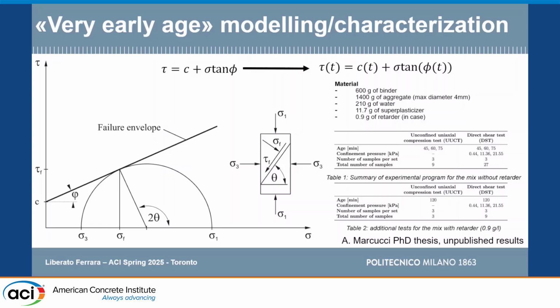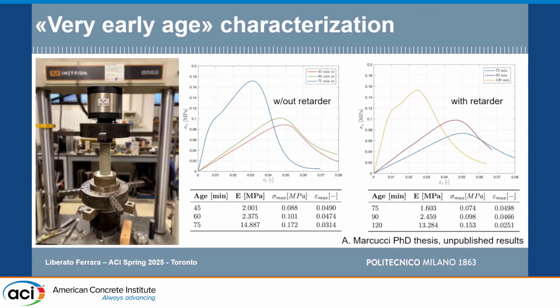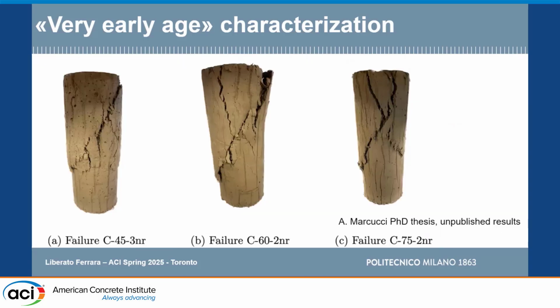So in some cases, for some climates, we had to use some retarder and wanted to see also the effect in this case. So these are some of the results for the compressive stress curves that we got, and you see here the typical shear band localization that we experience in compressive tests of cohesive or frictional materials like concrete.